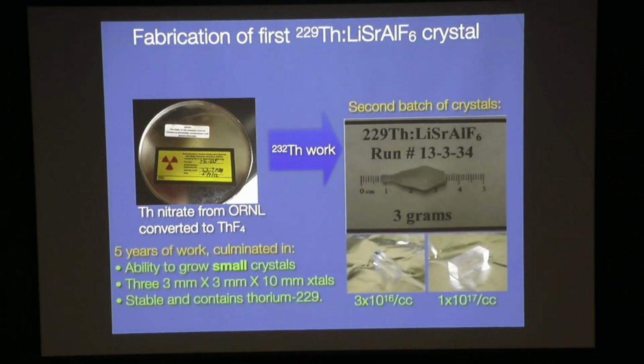And then we worked for about 5 years to be able to survey what we thought were the best crystals and then learn to grow them and dope them with thorium. So it's about 5 years of work to produce these little guys, which to me are roughly priceless. They have 10^16 to 10^17 thorium-229 atoms doped into them. They're transmissive down to at least 140 nanometers, and they are stable, which was something we were very worried about.